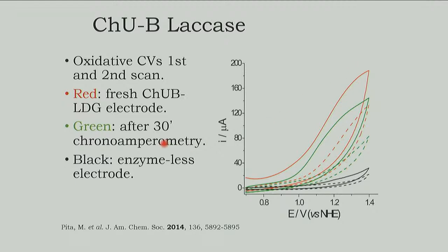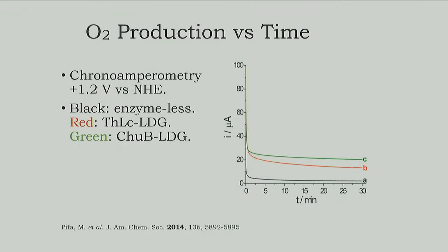This ChU-B enzyme was performing much better than the Trametes hirsuta laccase. The other one was at these current values at the maximum, so it was more than double. And after 30 minutes, it was still more active. And here we can see, in an experiment as a function of time, the higher current we were getting.